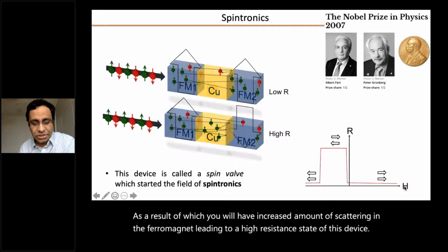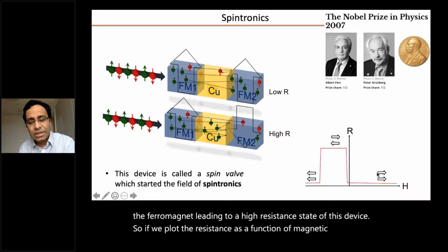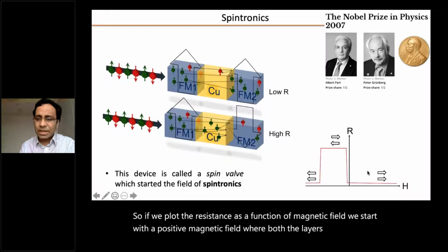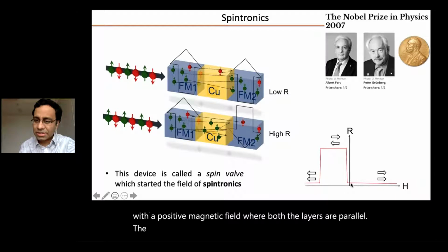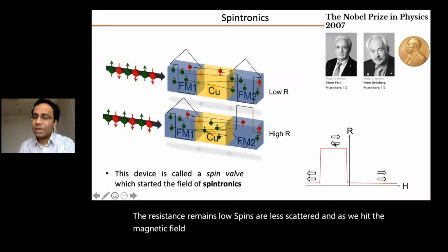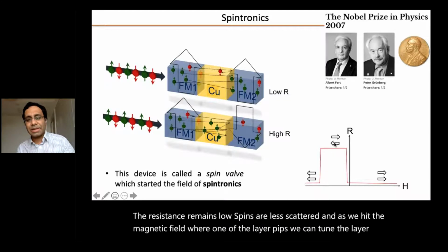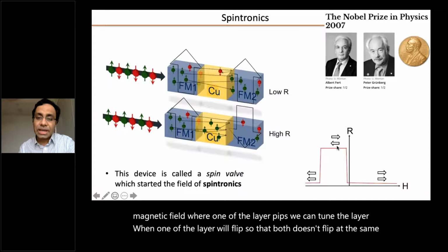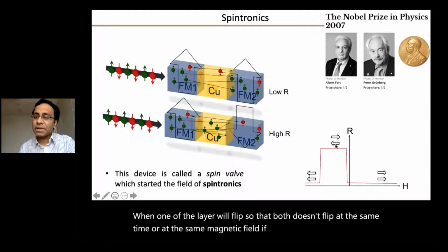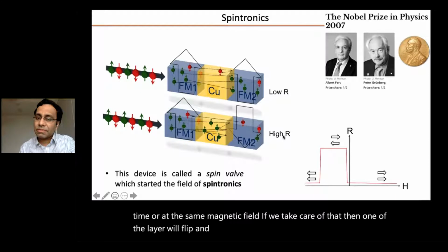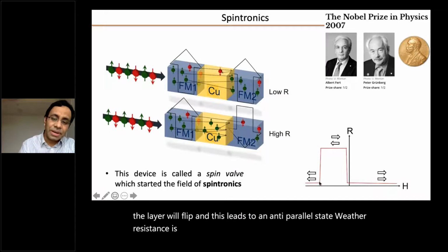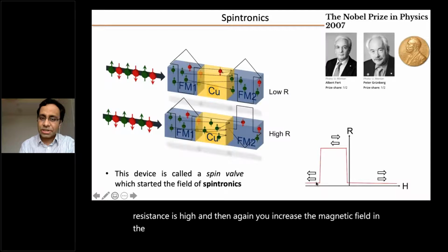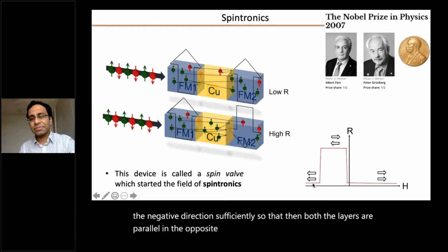So if we plot the resistance as a function of magnetic field, we start with a positive magnetic field where both the layers are parallel. The resistance remains low, spins are less scattered, and as we hit the magnetic field where one of the layers flips, we can tune it so that both don't flip at the same magnetic field. If we take care of that, then one layer will flip, and this leads to an anti-parallel state where the resistance is high. Then again you increase the magnetic field in the negative direction sufficiently so that both layers are parallel in the opposite direction and the resistance will come down.